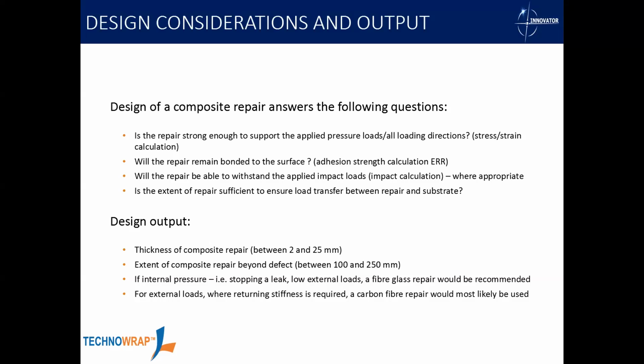We've got a few examples at the end where it's getting close to 2 inches thick, but generally they'll come out well less than an inch, normally half an inch or less. Then we get the length of the composite beyond the defect. Usually that's around 4 inches either side of the defect. And then you have a taper as well, which is roughly 1 inch. So in total, 5 inches either side of the defect is a rough number.